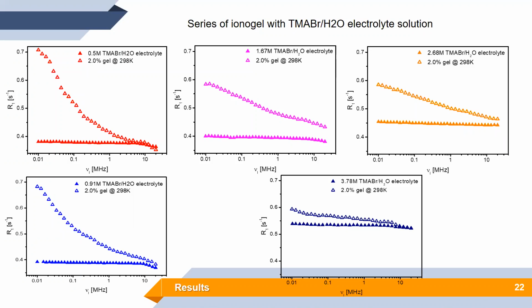For a low concentration of the salt, up to, let's say, 1 molar, we observe a very similar NMRD shape and also similar relaxation rate, which is around 0.7. And for the high concentration of the ions, we see that the NMRD profile shape is changing. This is mainly due to also a shift of the NMRD profile for a pure electrolyte solution, but the value of the relaxation rate, especially at the lowest field, stays on the same level.